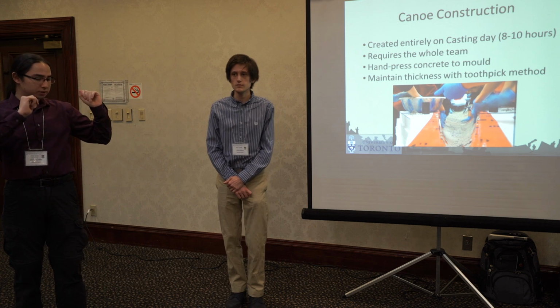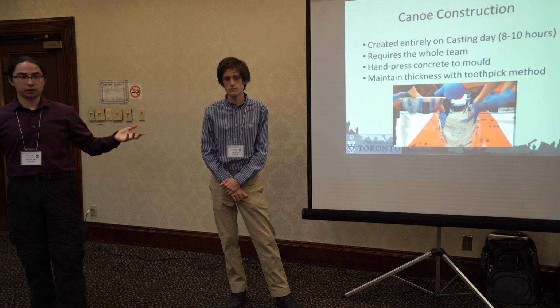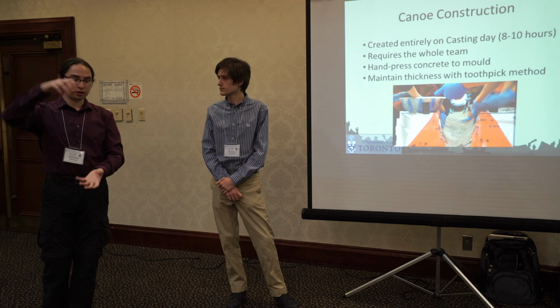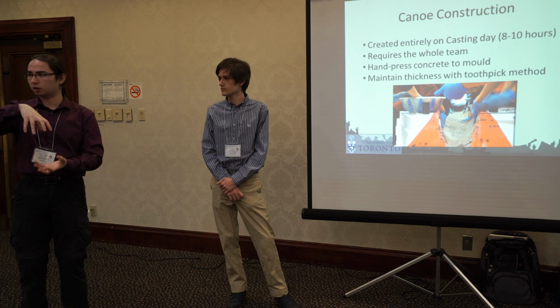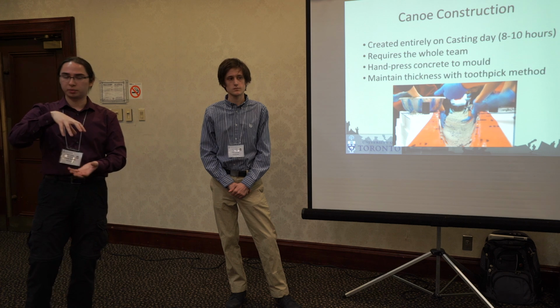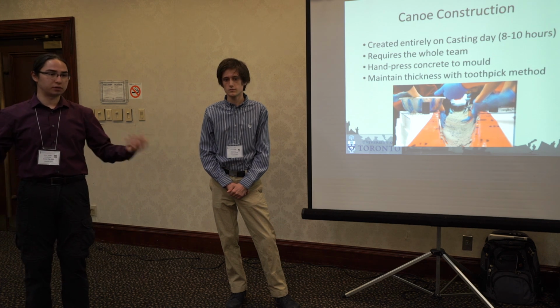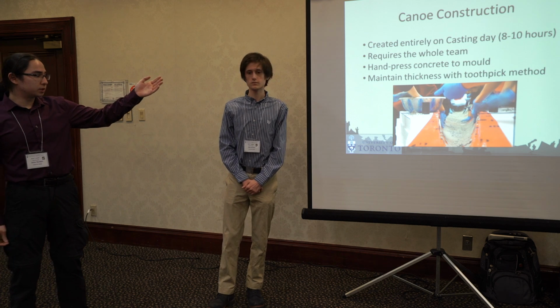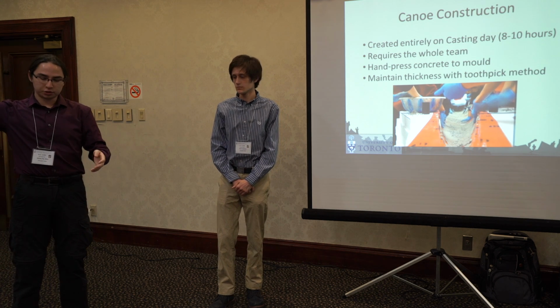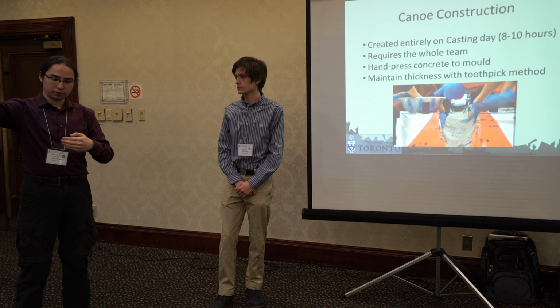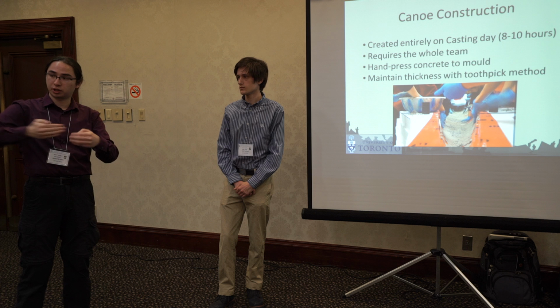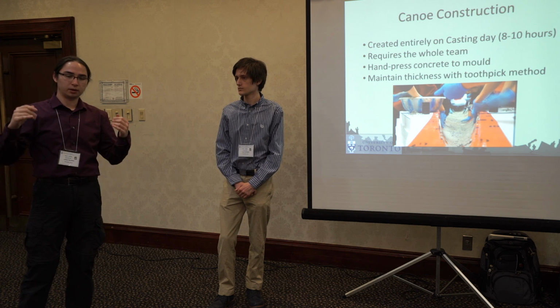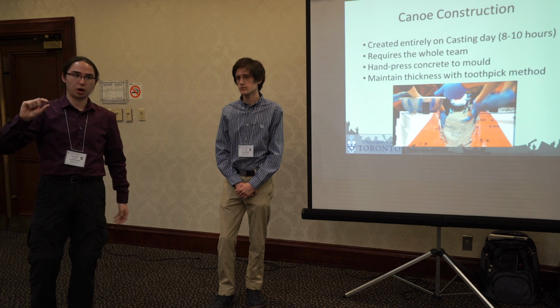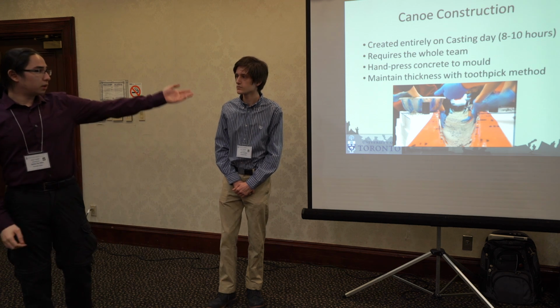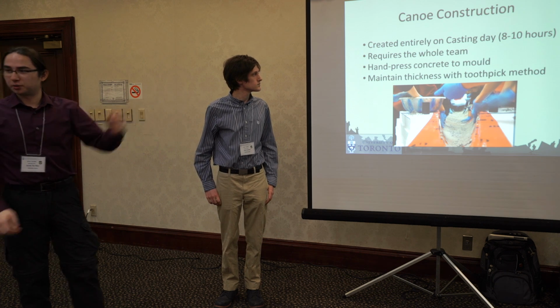Essentially how that works is, before the actual event, we have the main concrete leads of that year pre-bag all our concrete mixes, so we have each individual 4-liter bag of pre-mixed concrete. Then on the day, all we do is add our water mixtures and our admixtures to increase the speed of casting. We cast the finishing layer, then cast the structural layer on top of that in multiple stages. Before the finishing layer is finished, we start with the structural layer to ensure that the concrete has not set and we can get good bonding between the layers.